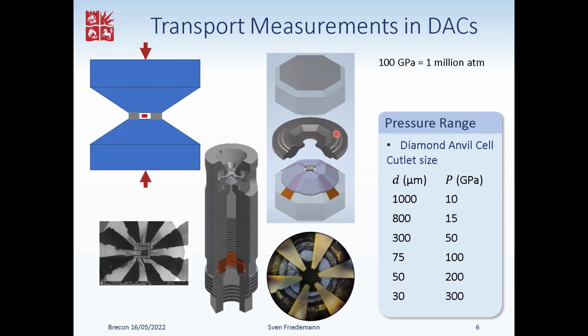One challenge with the electrodes in the diamond is that we use gaskets. You do need a gasket indeed, both in order to confine the sample space as well as to protect the anvils. In fact, we use a metal gasket. We need the malleability of metal for that and the tensile strength of metal, such that we can indent with the diamonds into the gasket without it splitting. If it was to split, the diamonds would touch each other and they would just crush each other. So we really need this strong, high tensile material, yet with some malleability, to provide us a gasket. So pretty much no way around metal.